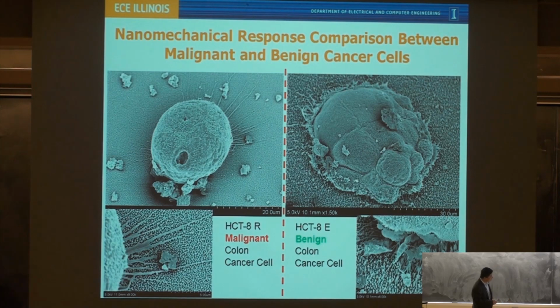We can see that, especially for these malignant colon cancer cells, it starts to really reach out very long filopodia or long tentacles. However, for the less aggressive colon cancer cells, it has much shorter or much fewer filopodia extended out. Another thing is you can see that most of these malignant cells tend to stay on the surface without spreading too much. However, the benign cell lines tend to cluster together, also spread out.